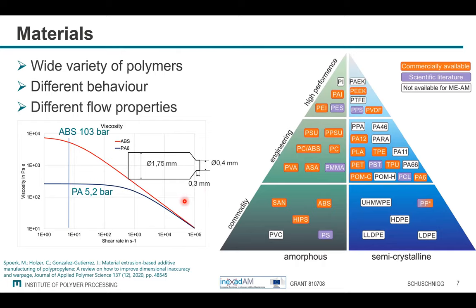Let's see the example for ABS and for polyamide. Both are used in additive manufacturing, and I just selected some of them out of a database. At a shear rate of 80 reciprocal seconds, the polyamide would need 5.2 bar with the FFF die and the ABS 103 bar. So it's a huge difference in the processing of different polymers. These are just two examples, but for additive manufacturing you would not select this ABS. You would go for another ABS type, perhaps with a lower molecular weight and therefore lighter flowing.